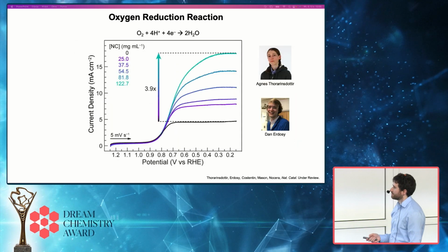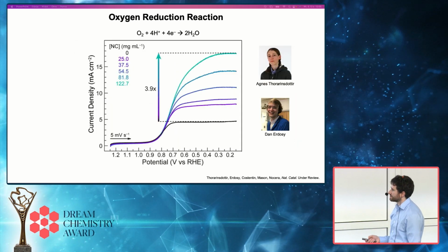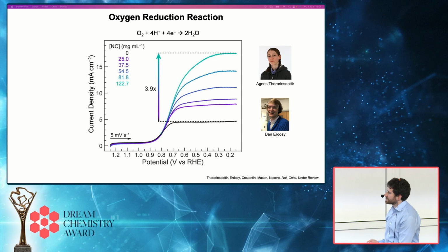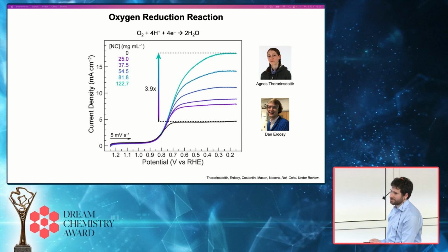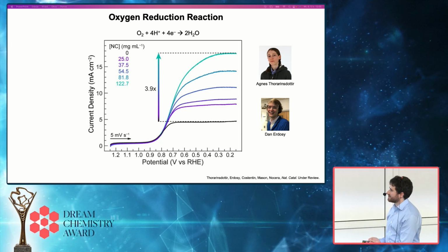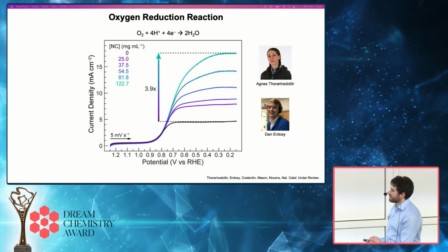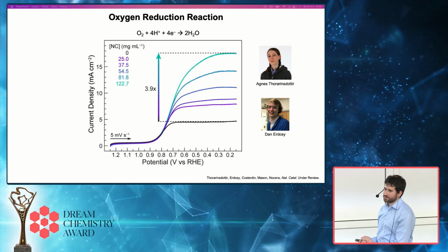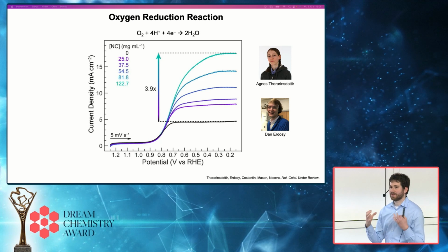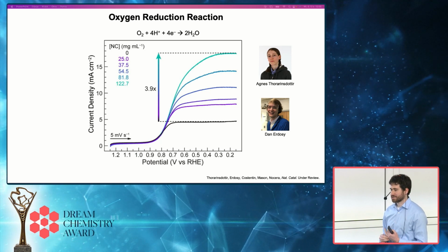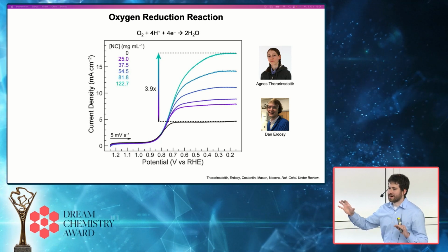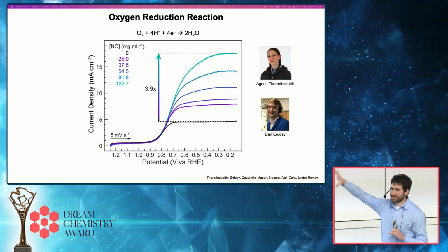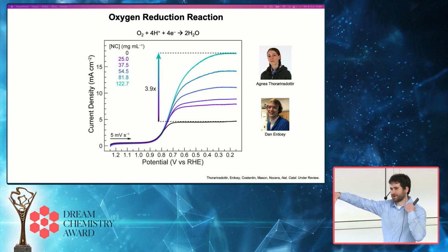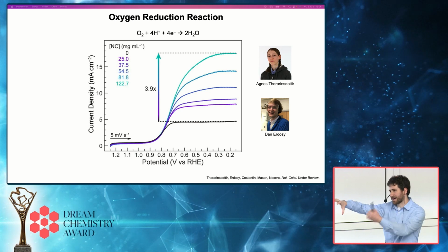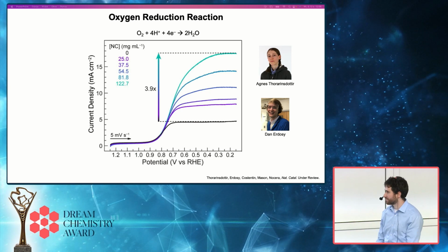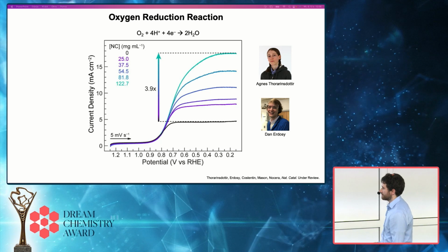There's a platinum catalyst on the electrode that serves as the catalyst for ORR. And so what we found, working with a postdoc in Dan Nocera's group, Agnes, was that as we increase the concentration of our silicalite-1 hydrophobic zeolite particles in these aqueous electrolytes, we see significant enhancements in the current density that we're able to achieve because we're removing a lot of these mass transport limitations for oxygen. So these solutions effectively serve as an oxygen buffer, and when oxygen is being reacted at the electrode surface, we have nanoparticles full of oxygen nearby that are rapidly able to release and replenish that oxygen. And so this allows us to get to much higher current densities.